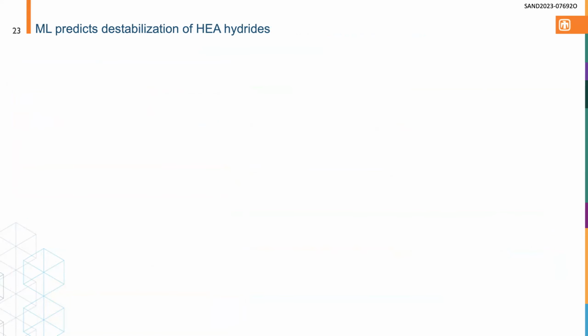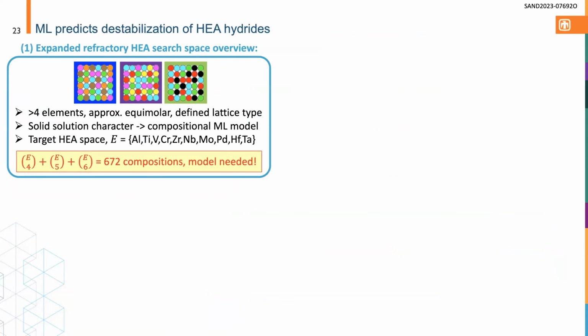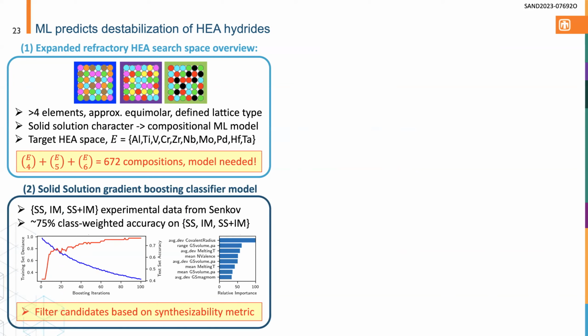So we can predict destabilized high-entropy alloy hydrides. What is a high-entropy alloy? It's essentially a solid solution on a well-defined lattice type with a large number of elements, typically greater than 4 by some people's definition, and there's random site disorder on that lattice. People have been looking at high-entropy alloys for hydrogen storage for a bit now. Even if you take a relatively small elemental space, there are 672 equimolar compositions. So you definitely need some kind of efficient surrogate model if you want to get an idea of their hydriding properties.